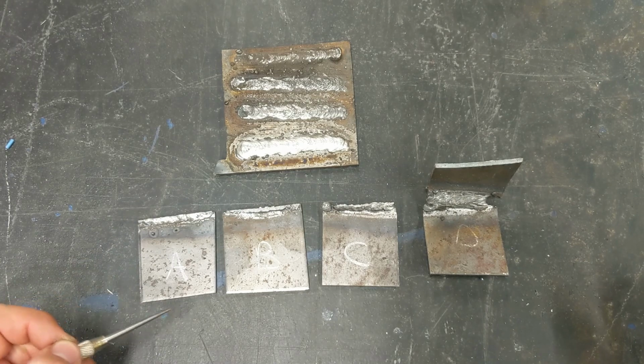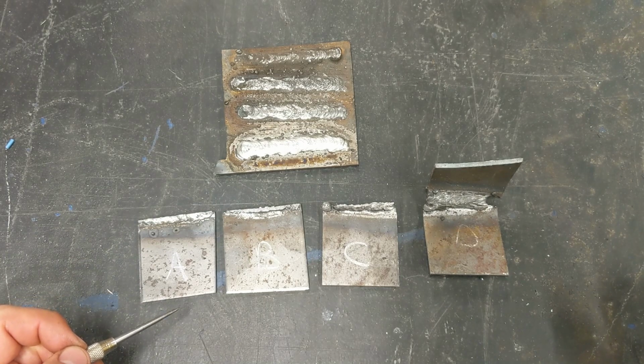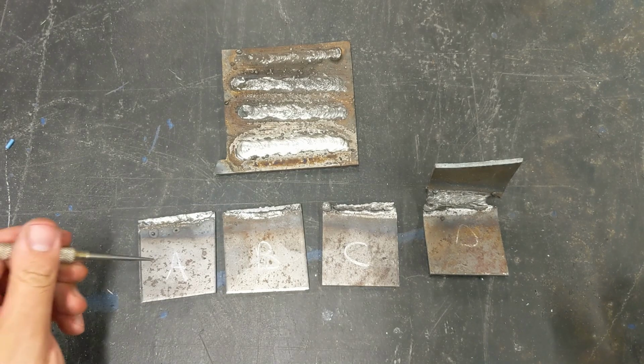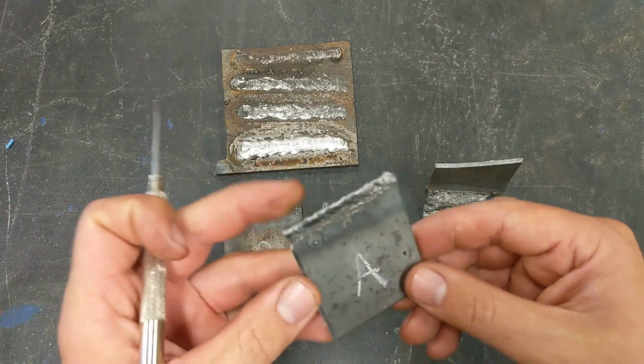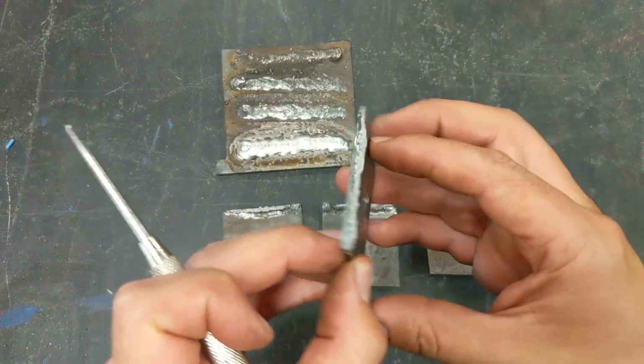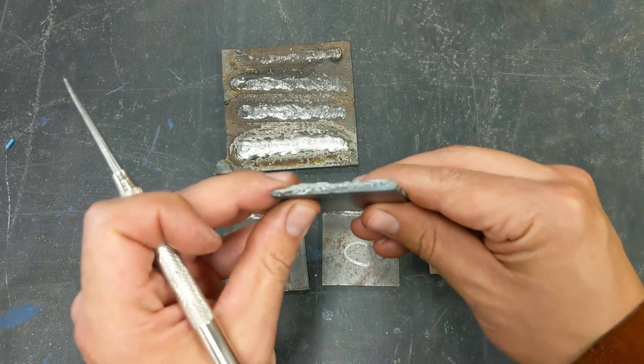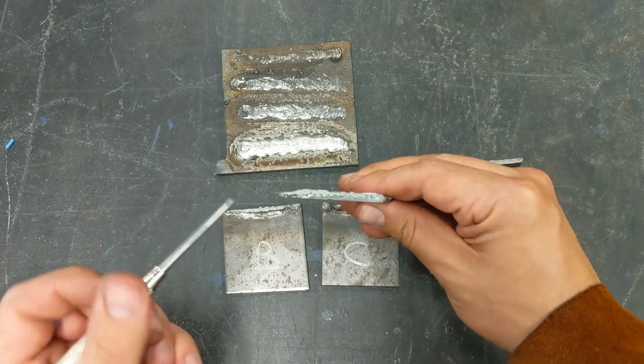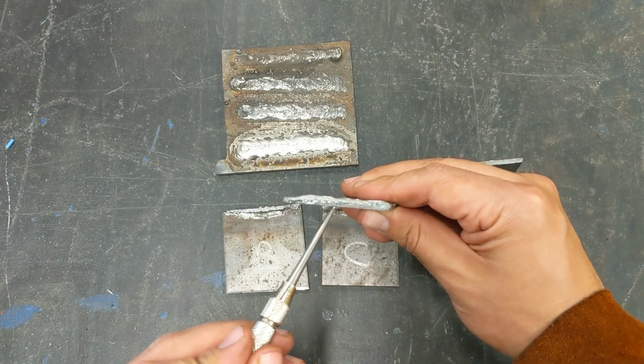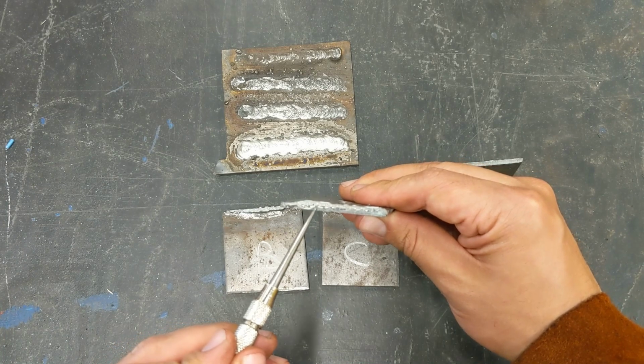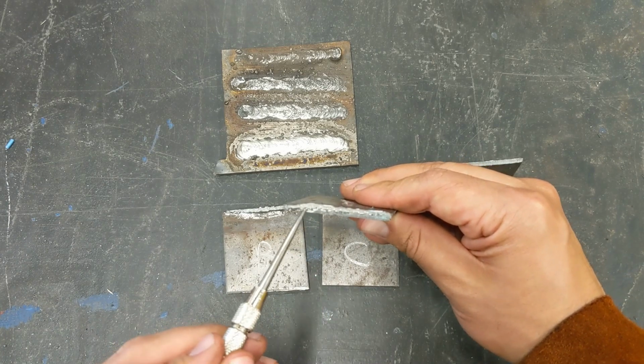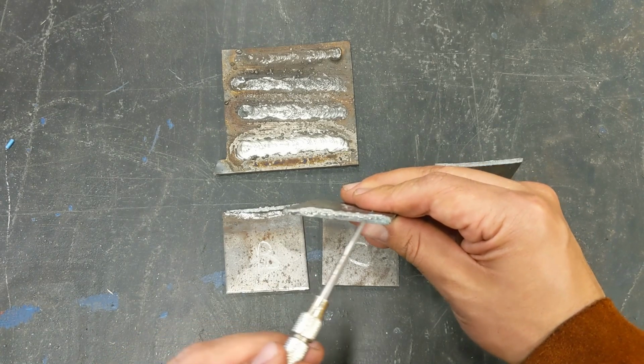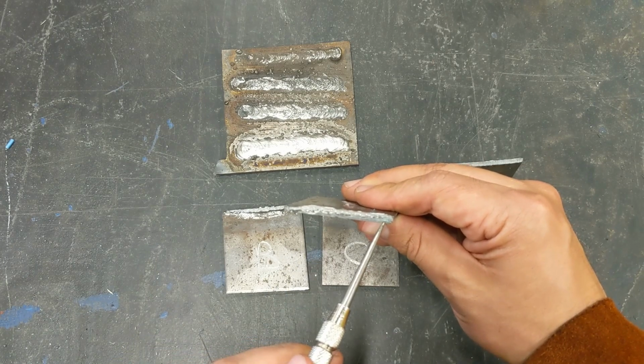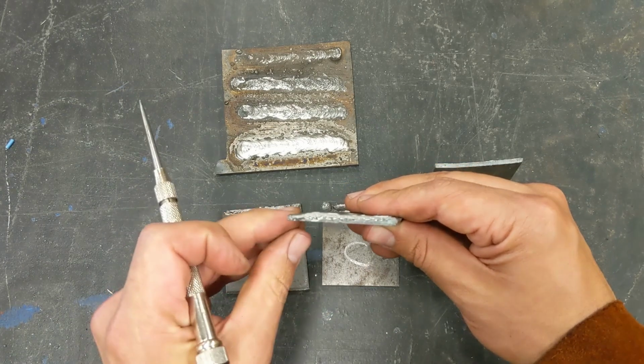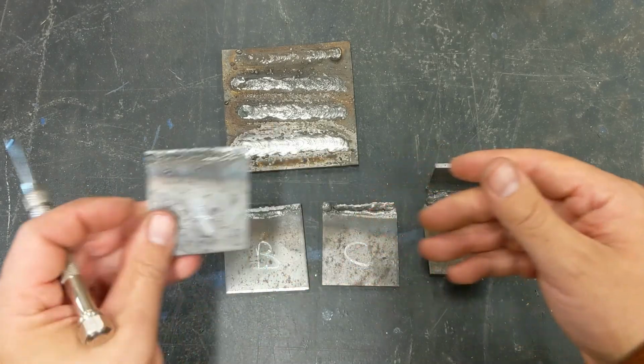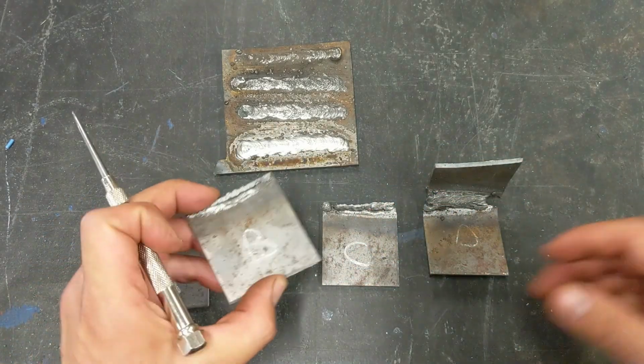But let's look at our 4 samples that were welded at 4 different amperages. Over here at 50 amps, sample A broke, and there is really very little weld penetration that occurs. You can see the weld bead up here, but the weld bead is relatively thin and didn't offer much strength. The biggest problem though was almost no weld penetration. That 50 amps just wasn't quite enough to get through the material.